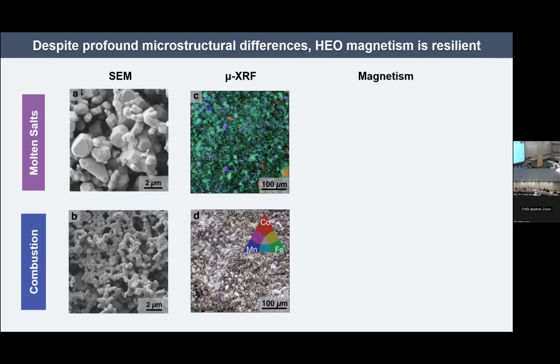Now, I want to introduce a technique which is called micro-XRF, so micro X-ray fluorescence spectroscopy. This is a measurement that we performed at the ESRF. What we're doing in a micro-XRF experiment is measuring the fluorescence signal from our sample, again with micron scale resolution. And we're performing a quantitative measurement, so we can look at whether the fluorescence signal across the sample is in proportion for each of our 3 elements.